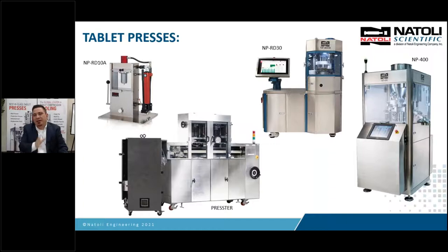And the Presster is highly instrumented for measuring pre-compression force, ejection force, main compression force, sticking force, radial die wall force. And the key thing here is we're measuring punch displacement. So as we are compressing that single tablet, we're measuring the in-die thickness in real time. And that data will allow us to look at work curves and Heckel plots, where the work curve will allow us to evaluate the elasticity, plasticity, or brittleness of the material. And the Heckel plot will tell us what the yield pressure is. So how much pressure is required to cause those particles to deform and start bonding.